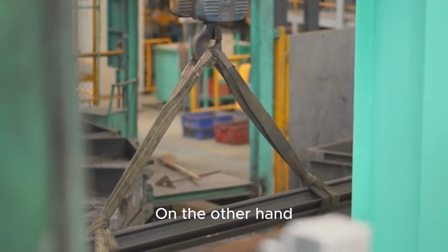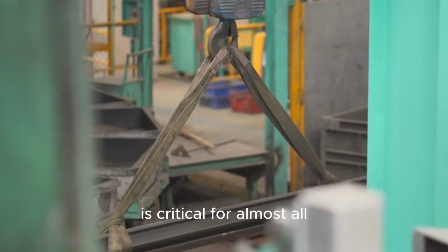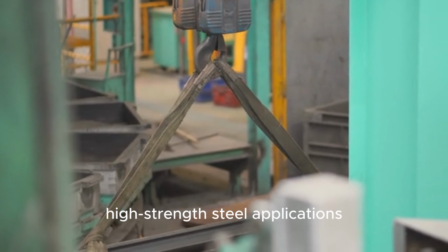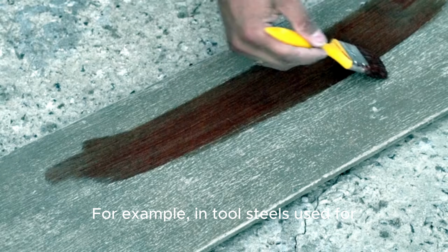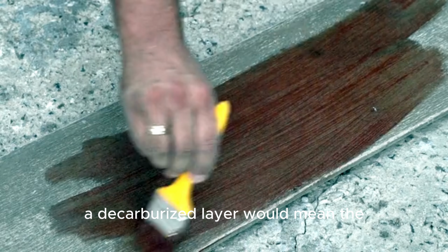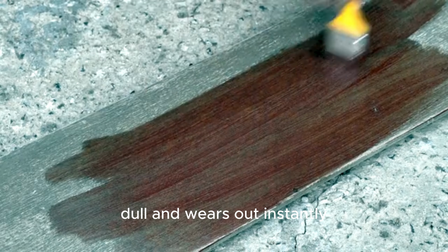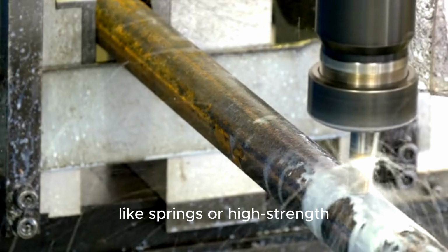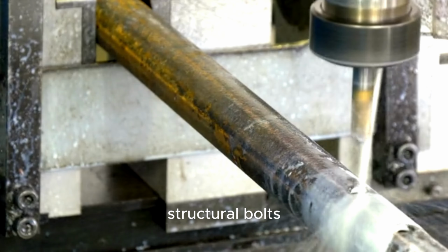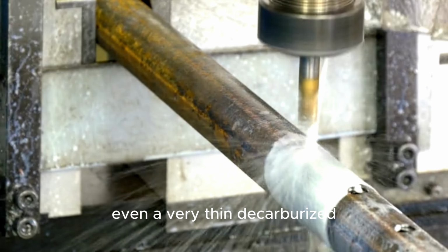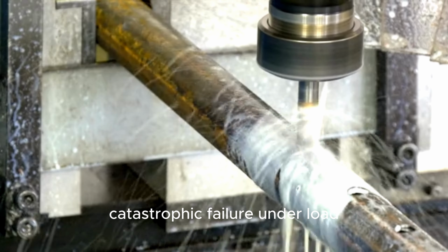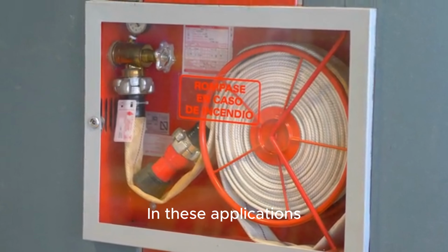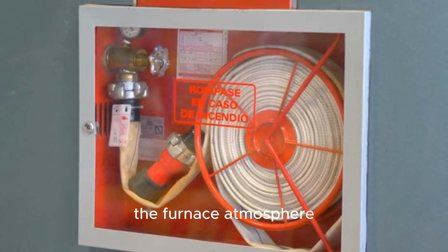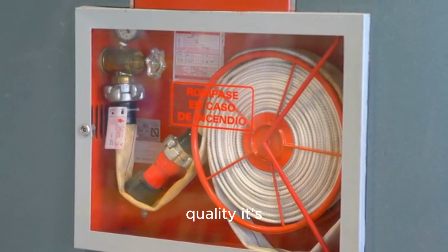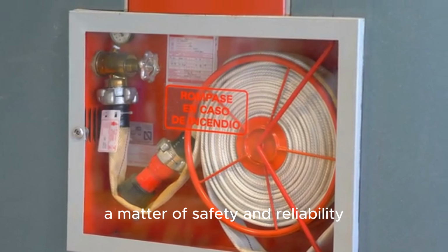On the other hand, managing and preventing decarburization is critical for almost all high-strength steel applications. For example, in tool steels used for cutting and forming, a decarburized layer would mean the cutting edge is dull and wears out instantly. For components like springs or high-strength structural bolts, even a very thin decarburized layer can be a starting point for catastrophic failure under load. In these applications, controlling the furnace atmosphere isn't just a matter of quality, it's a matter of safety and reliability.